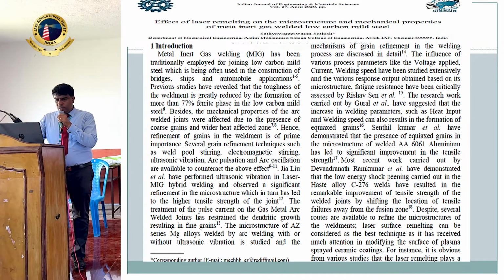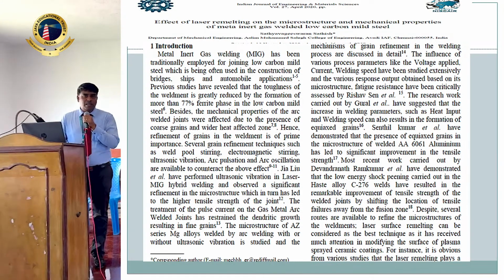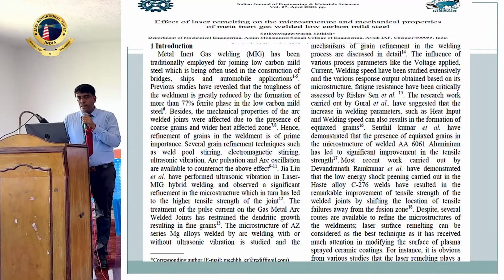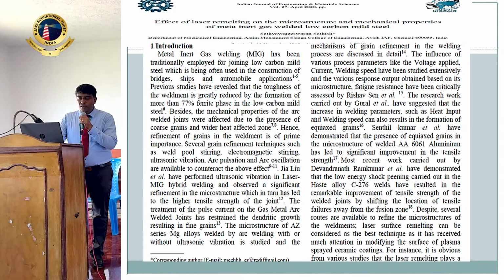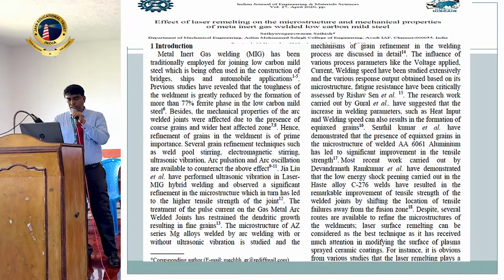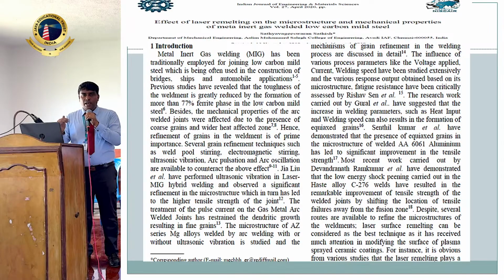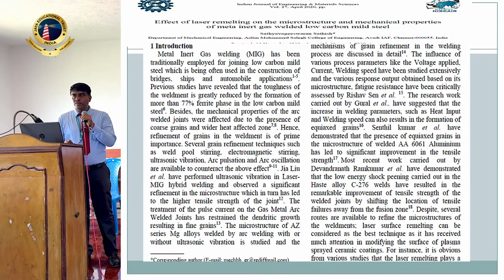Jia Liu et al. have performed ultrasonic vibration in laser MIG welded joints and observed a significant refinement in the microstructure, which in turn has led to the higher tensile strength of the joint. So this particular person has worked on laser MIG welding and found a significant improvement in the property. Likewise, I wrote that the treatment of the pulse current on gas metal arc welding has restrained the dendritic growth, resulting in fine grains. It is quoted by some others. Likewise, I have given a few current statuses of this MIG welding, and I told the reason with references.